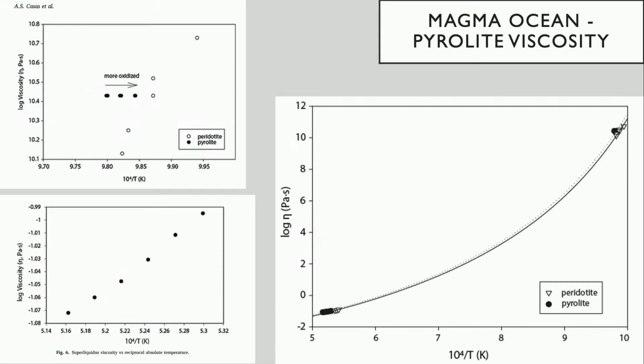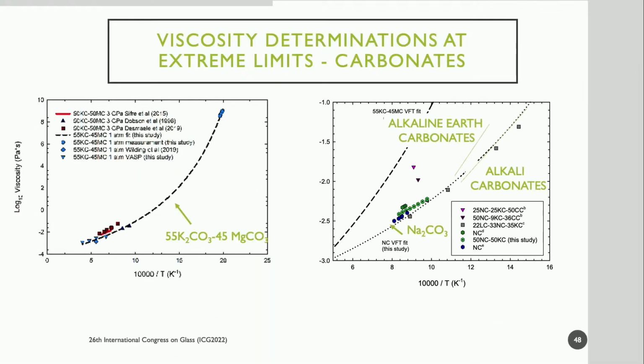And then we can take very high temperature superliquidus viscosity data for these systems using concentric cylinder methods, and we can add it to the calorimetric, dilatometric comparison. In other words, using the calorimeter to predict viscosity way down at the glass transition. And we can interpolate the value of the viscosity temperature relationship between these two areas. Now this is extreme. The reason there's no data between here and here is that this will crystallize. These are not good glass formers. So we've driven to an area now where we can even look at really poor glass formers.